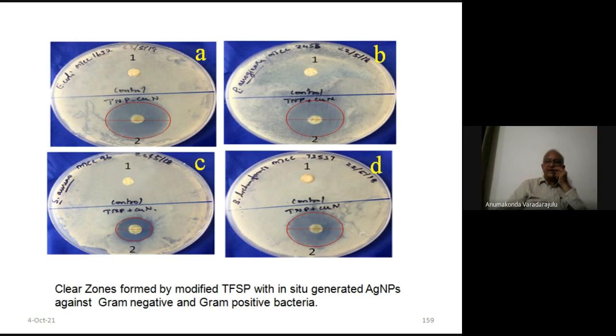And then antibacterial activity. It showed very good antibacterial activity here. This is unmodified shell powder, and this is modified shell powder against E. coli, and then other bacteria, gram-negative bacteria and gram-positive bacteria. So the unmodified powder did not show any antibacterial activity.